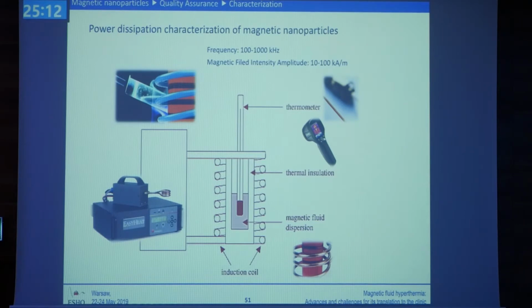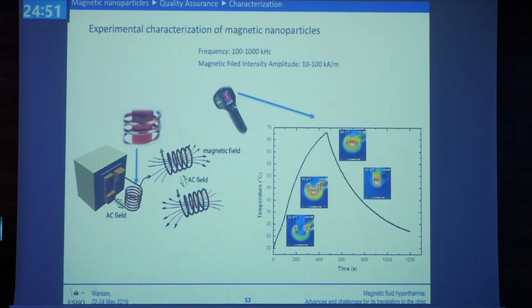the nanoparticle heating efficiency? We do that in the lab, and we can do it with cells inside the solution or without. And we use a coil, okay? We put the sample in there, and we use a thermometer. In this case, the thermometer is, of course, an optical fiber, okay? We also use infrared cameras to see the heating of the coil and also the heating of the sample.